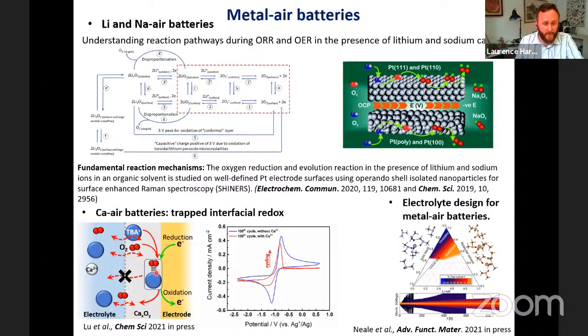And as it becomes trapped, it is then able to be readily oxidized again. So after, say, 100 cycles, you can see that our red peak here has grown very significantly. And so we have this trapped interfacial redox within this system. And the blue trace is just the conventional signal you get when you don't have any calcium present at all.